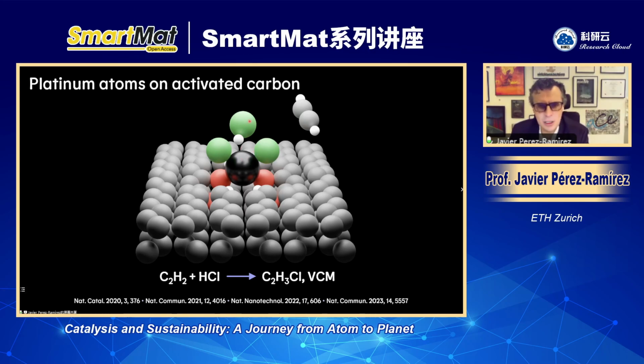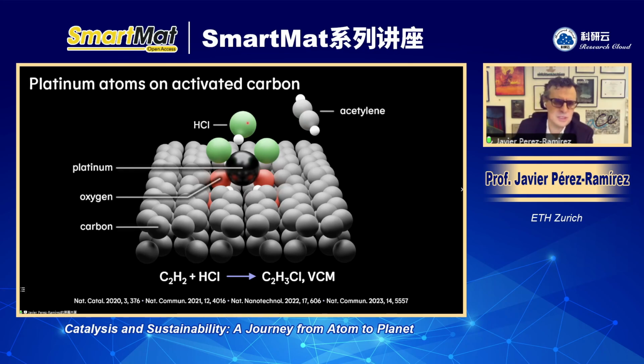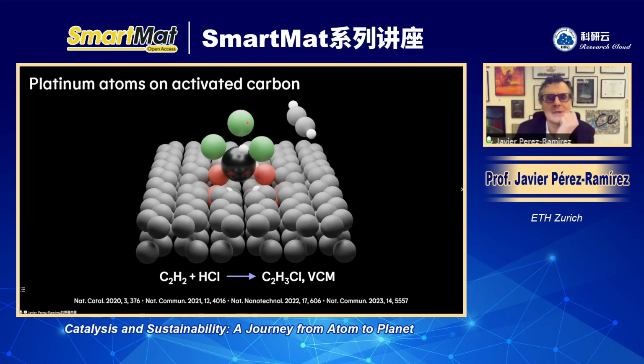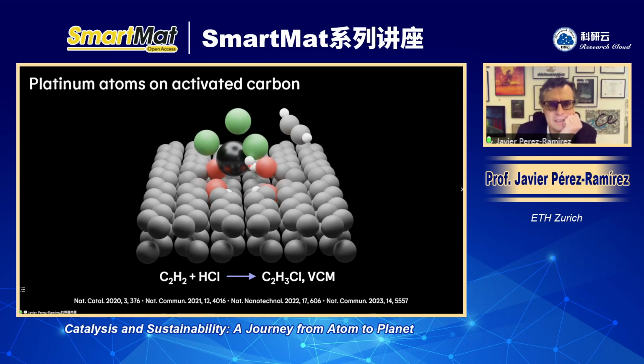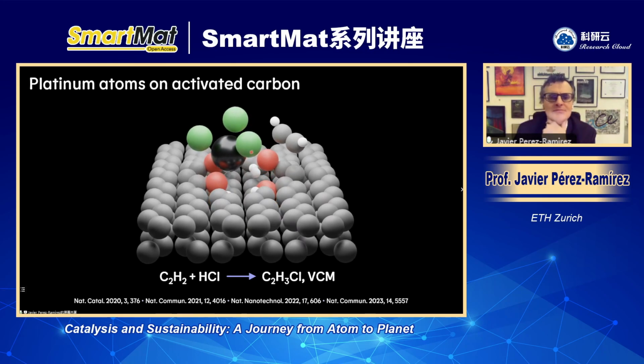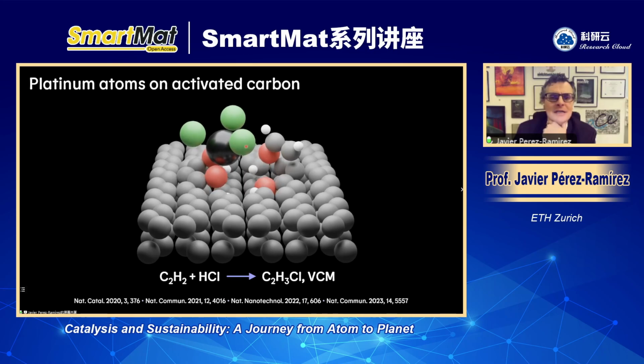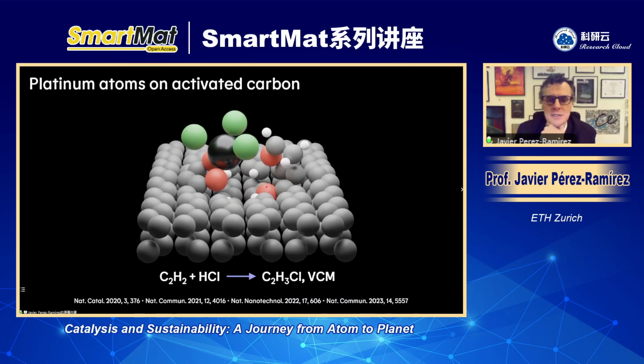And this material catalyzes very effectively the reaction between acetylene and hydrochloric acid. And the reaction actually proceeds like this. So these are the different elements of the reacting system that I'm going to describe. And you can see what happens, right? Hydrochloric acid activates on the platinum atom and delivers the chlorine, chlorinating further the single atom. And the hydrogen actually goes to the oxygen functionality.